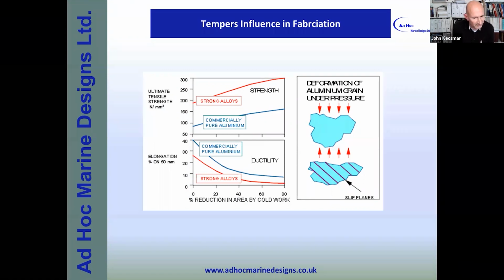And this uses the slip planes within the alloy matrix to dislocate and move the crystalline structure to become much closer together. What this means is that the dislocations then become entangled with each other, thereby forming obstacles to further dislocation motion, and hence they increase the stress. But also it reduces the ductility, as I was mentioning before.